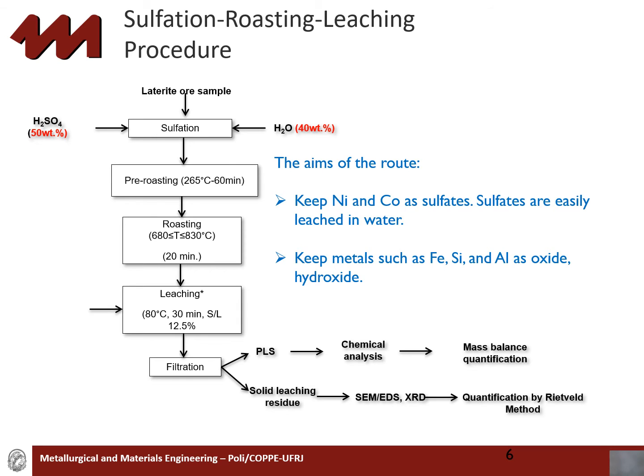The pregnant leach solutions will be carried to make the chemical analysis and finally the mass balance, while the solid leaching residue will be analyzed by SEM EDS, scanning electron microscope and EDS, plus XRD. Finally, the samples were quantified by the Rietveld method.